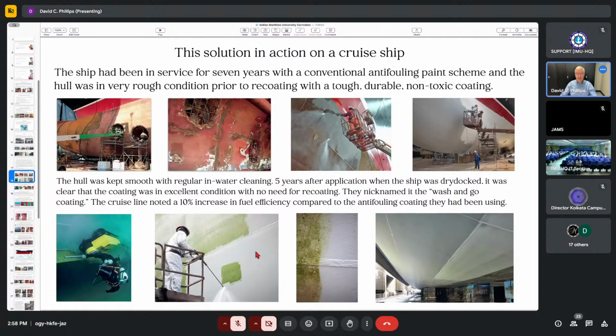Added advantage was this kind of coating, it was completely non-toxic. So they were not damaging, contaminating the environment in the ports that they would sail to. They gained PR value from it of, hey, we're a completely green ship. When we go to Aruba or something and we dock for 3 days, we do not emit any chemicals into the water. But you see, they solved their corrosion and other problems at the same time. Many years on, they still had the same coating on. It was the original. They didn't change it.